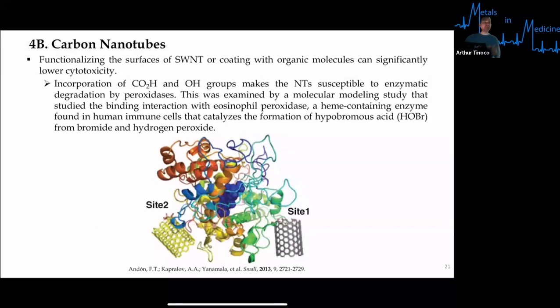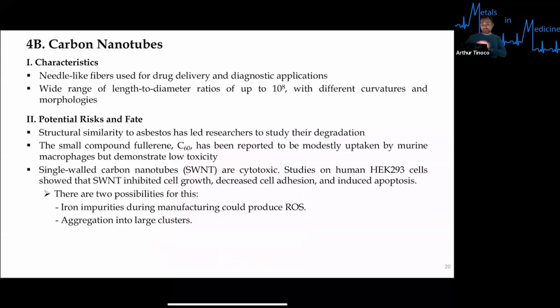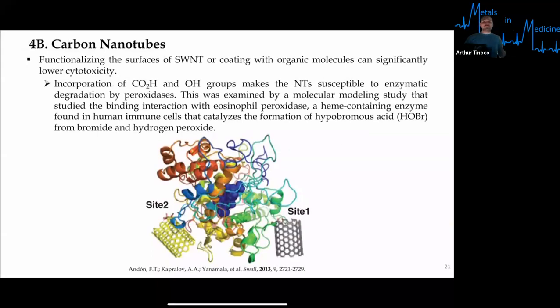And so here we have an example from a 2013 study: functionalizing the surfaces of SWNT with organic molecules. So here we're looking at the incorporation of carboxylate or hydroxyl groups that makes the nanotube susceptible to enzymatic degradation by peroxidases. And so that goes into what Javier was talking about, this idea that you want these materials to be cleared from the body, whether your body has a capability of just taking them and clearing them, or has the capacity to break them down in such a way that doesn't lead to the formation of anything that will harm the body and still can basically lead to their being cleared.